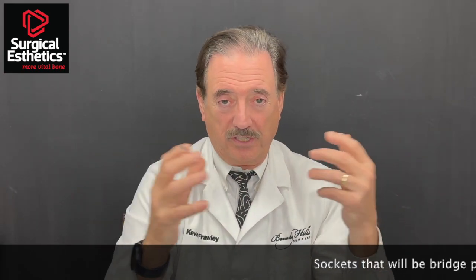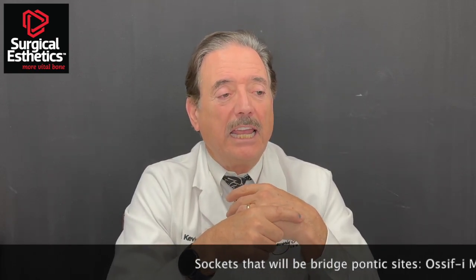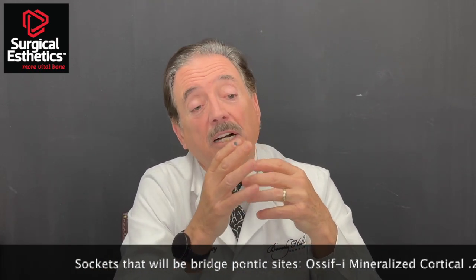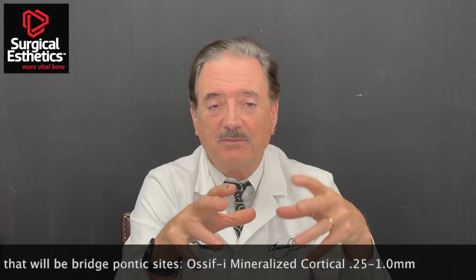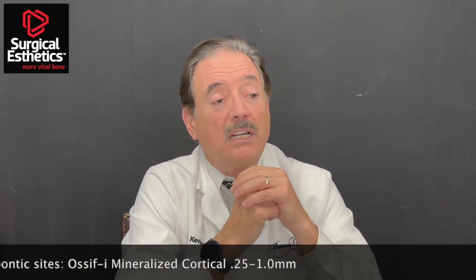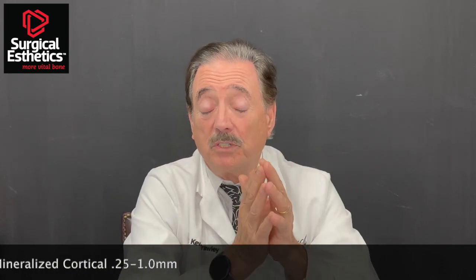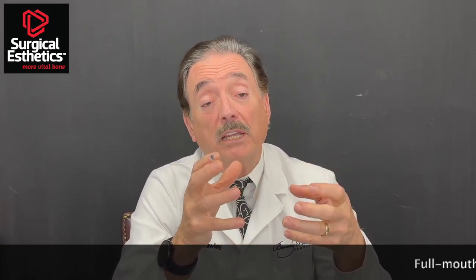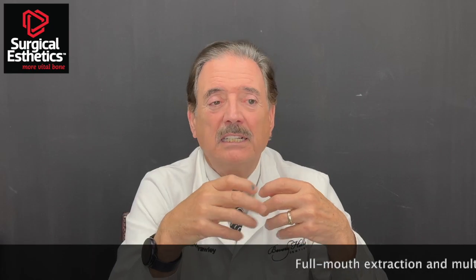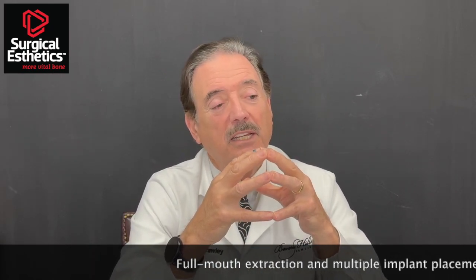Let's say in an area where you've got a defect and you're going to do a bridge. Tooth came out, you're going to do a bridge there. Again, you don't want that area to become a big concavity where the pontic has got to drop into that space. So that's an area where I potentially would use a Ossifi cortical material. And the cortical, again, is dense particles that will resorb very slowly. And that's perfect for a pontic space, because you want that space to really resorb slowly. It would resorb too slowly, in my opinion, for placing an implant there. But for a pontic space, that would be an ideal material.